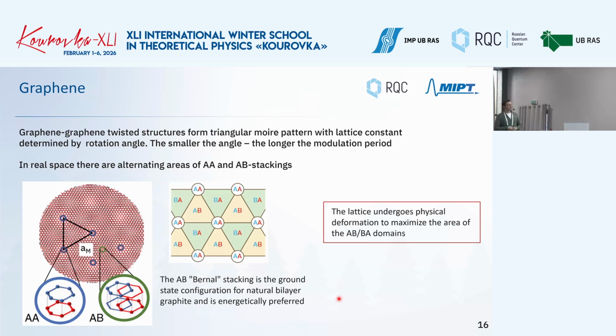So what happens next, if you take the graphene twisted structure, it may form a triangular moiré pattern with the lattice constant, as we discussed, depending on the angle. Also, the smaller the angle of rotation, the longer the modulation period. And in real space, you see that there are different areas, the so-called AA and AB stacking. In the case of AA, the atoms are just on top of each other. And the AB state is energetically more favorable, the so-called Bernal stacking. So this moiré potential makes this type of structure.